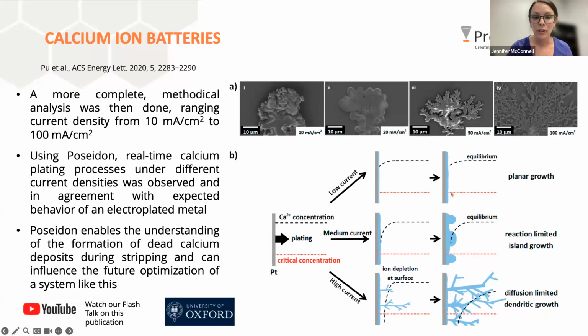They found that with lower current densities, you're able to get more planar, even growth, which was better for redissolution. You'd have more complete redissolution. As you went up in current density, with these more classical dendritic growths, you have branches that can easily break off and cause dead calcium, which leads to the situation we were just talking about, where the battery life recedes every time that happens. So understanding current density and its effect on dendrite growth, and how that affects battery life, you're able to actually visualize it.